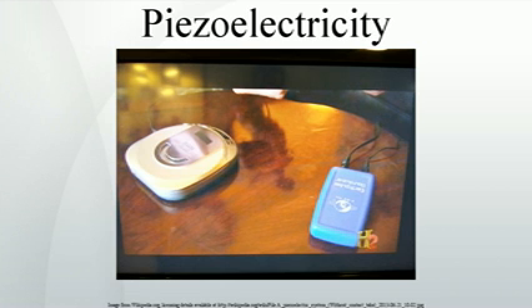Bone. Dry bone exhibits some piezoelectric properties. Studies of Fukada et al. showed that these are not due to the apatite crystals, which are centrosymmetric, thus non-piezoelectric, but due to collagen. Collagen exhibits the polar uniaxial orientation of molecular dipoles in its structure and can be considered as a bioelectret, a sort of dielectric material exhibiting quasi-permanent space charge and dipolar charge. Potentials are thought to occur when a number of collagen molecules are stressed in the same way, displacing significant numbers of the charge carriers from the inside to the surface of the specimen.